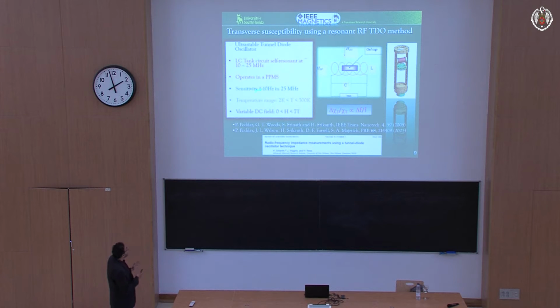The sensitivity is very high because it's a frequency measurement, and students, experimentalists in the audience should know that frequency is perhaps the most accurately measurable physical quantity. Ideally, you want to measure any physical quantity using a frequency probe. So that's what we do here. It gives us a good sensitivity. With a frequency counter, we can detect shifts in the resonance frequency of the circuit of the order of a few hertz in an overall resonance of 25 megahertz. You do the math, you can get parts per million resolution when looking at very fine magnetic phase transitions. So we've used this technique for many, many years for looking at all kinds of magnetic materials, certainly nanoparticles. This is a very effective way of measuring the important quantities, namely the switching fields and the anisotropy fields in magnetic materials. So why transverse?